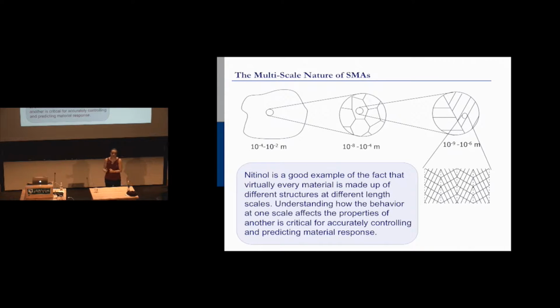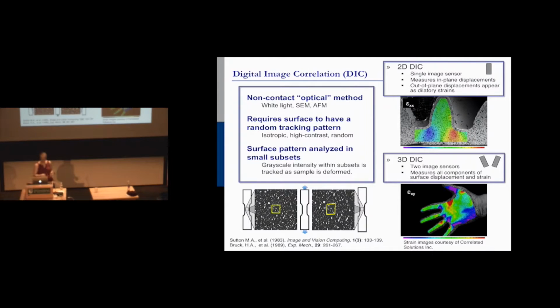The great thing about this material, too, is that as we're developing these things, there's a lot of symmetry relations that we can use to understand what's being formed and how it's interacting with its local environment around it. So one of the ways that we can quantify strain, you guys saw in the picture where the austenite was like a 0% strain and the martensite was a 6% strain. So strain is a huge indicator of transformation in these materials, and an indicator of the extent of transformation. We can actually associate a transformation strain.